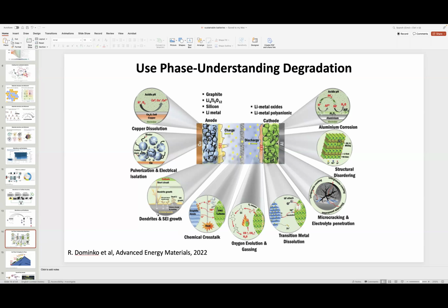We can have, on the anode in particular, dendrite growth and the SEI formation, which we need to control and understand so it keeps the electrode together and ionically conductive. Talking about SEI, we can have a lot of crosstalk between the SEI happening on the cathode and the SEI happening on the anode, and things moving around between the two. And also we could have some heat generation when things degrade here. Gases are evolved, which lead to this heat generation, but also swelling and explosion of a battery, different electrolytes decomposing to different chemicals and causing all sorts of problems.